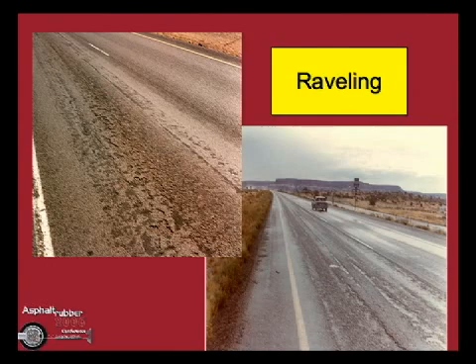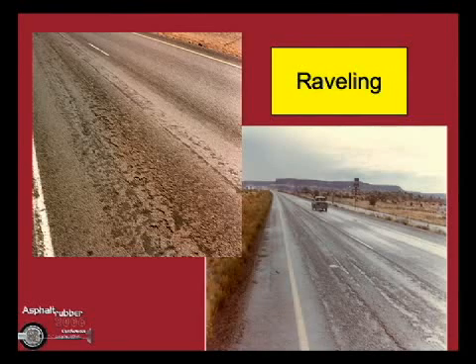Raveling is another issue. Fortunately, we don't see much of this in Arizona anymore, but many years ago, the Federal Highway Administration, and I think wisely so, promoted the use of open graded friction courses as a safety means of getting us safer highways. And a lot of states tried this. Arizona and California had used them for many years. But one of the problems with open graded friction courses is that they do tend to ravel. The reason is that you can't really put too much asphalt into an open graded friction course, at least not if you use regular asphalt, because it all runs off, and then you have a bleeding situation. So you're always between either raveling or bleeding. You'll see later that the adoption of asphalt rubber for open graded friction courses really has prevented this from occurring.